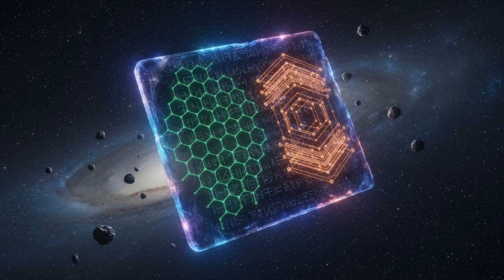By applying a tiny gate voltage, essentially a small electric field that adds just a few extra electrons to the system, the material transformed from an insulator into a superconductor. It conducted electricity with zero resistance. Now the critical temperature was very low, about 1.17 Kelvin. That is extremely cold, but what mattered was the density. Standard superconductors need billions of times more electrons to carry the current. This magic angle graphene was superconducting with a skeleton crew of charge carriers.